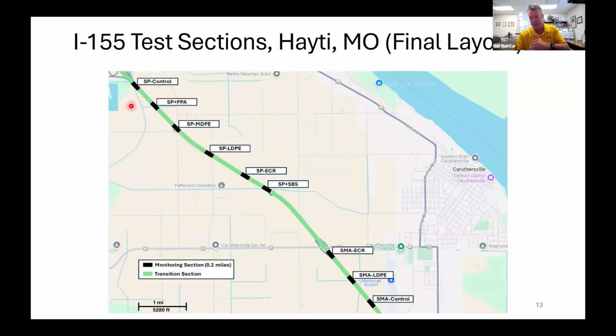Most of our sections are on the eastbound. If you ride back on the westbound, that's all control sections. The passing lanes are all control sections. And we looked at things like SMA versus dense graded for high traffic. We looked at SBS polymer versus PPA modification, polyphosphoric acid, to get a stiff performance graded binder, versus recycled plastic and recycled rubber. So we also looked at scrap tires here as well.